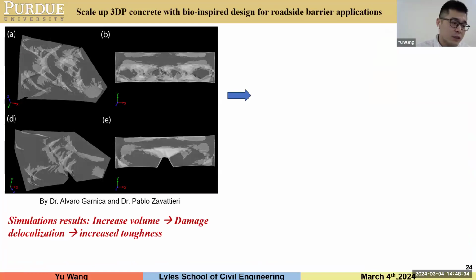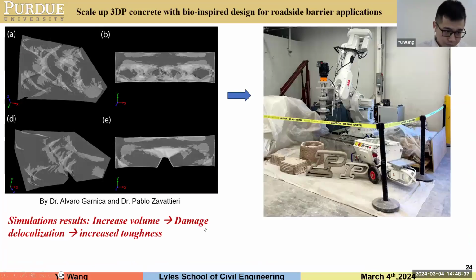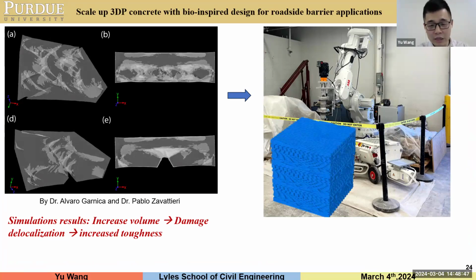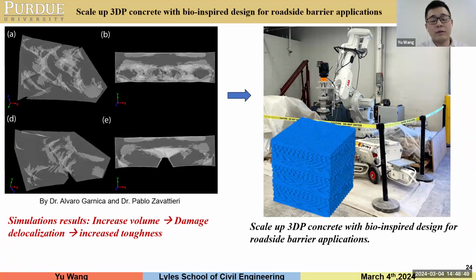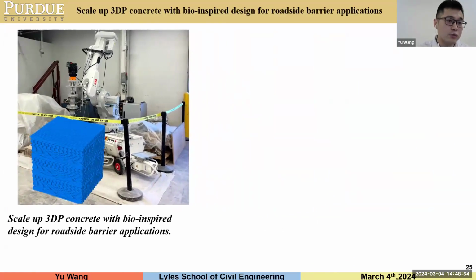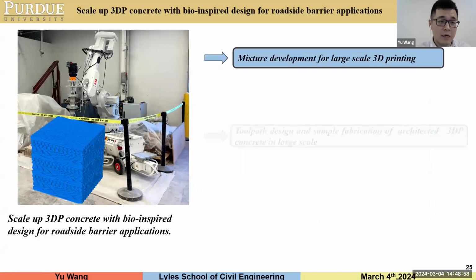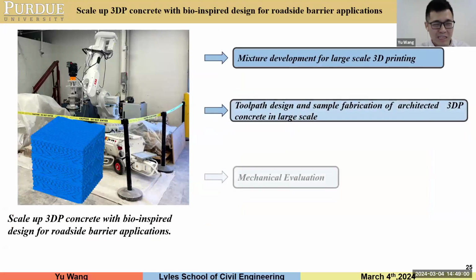Because in the simulation, we found that if we increase the volume of the sample so we get enough interface, it will promote micro crack development to increase the toughness and energy absorption capacity. So we scale this up to large scale to test the energy absorption capacity, which can potentially be used for roadside barrier applications. But large scale is more complex than small scale.